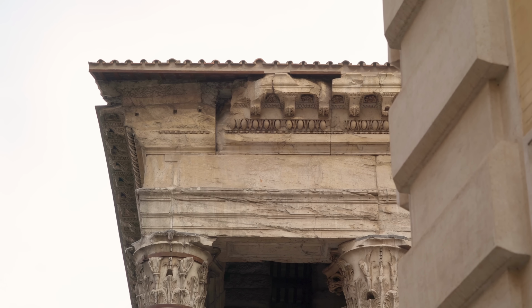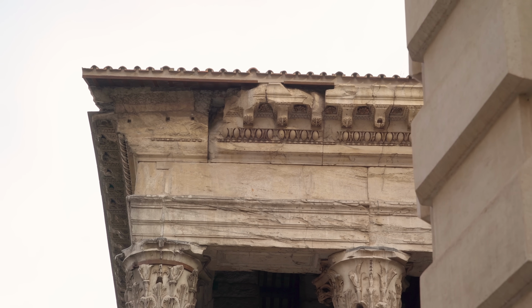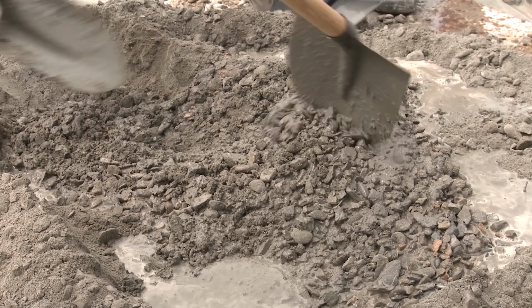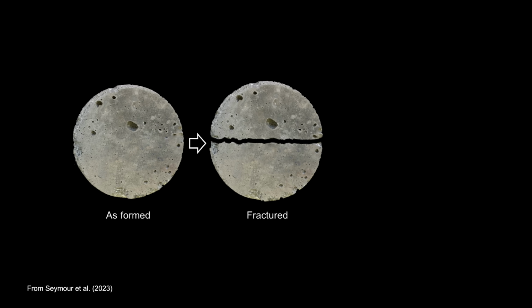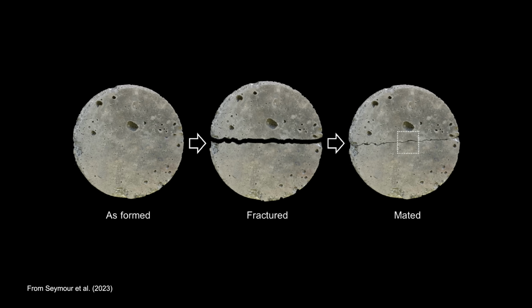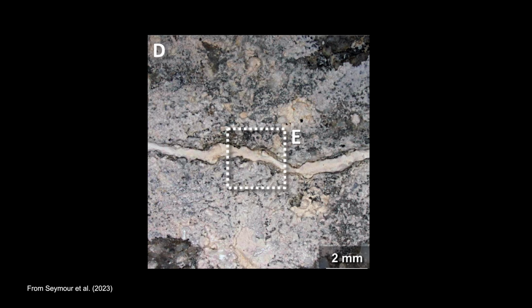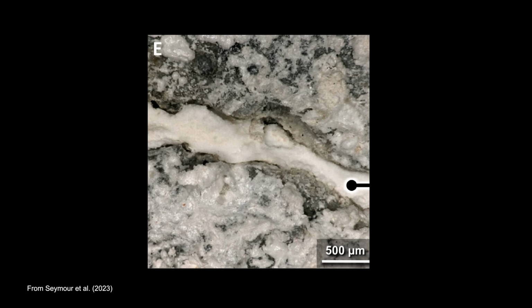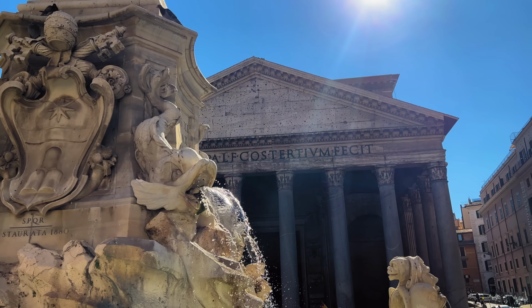So was Roman concrete superior to modern concrete? Well, the answer is no, in short. I mean, there were some surprising advantages that Roman concrete had. For example, it was actually less well mixed than modern concrete, so there were little blocks of undissolved calcium oxide, or quicklime, that remained inside Roman concrete. And then what happened is, when the concrete cracked and water got in there, it would dissolve that calcium oxide, forming calcium hydroxide, and then you would get the new growth of calcium carbonate. So Roman concrete was actually self-healing. That's kind of a fascinating advantage.